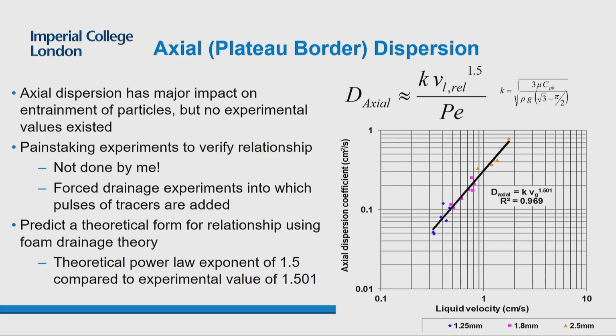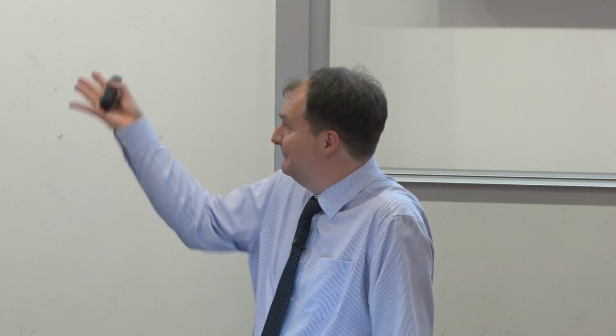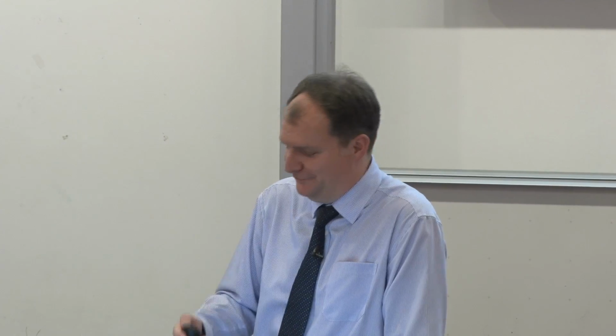Because nobody had studied this before, we did some experiments. Well, strictly speaking, a PhD student did some experiments, and I did some analysis of the experiments afterwards. What we did was we took the foam drainage theory and used it to predict what these dispersion coefficients should look like. I got the relationship which said that this dispersion coefficient should be proportional to the velocity raised to a power of 1.5. And the experiments, well, actually for once, the real world tended to agree with what the theory said, and we got an experimental value of 1.501, which is pretty close to what the theory had predicted.